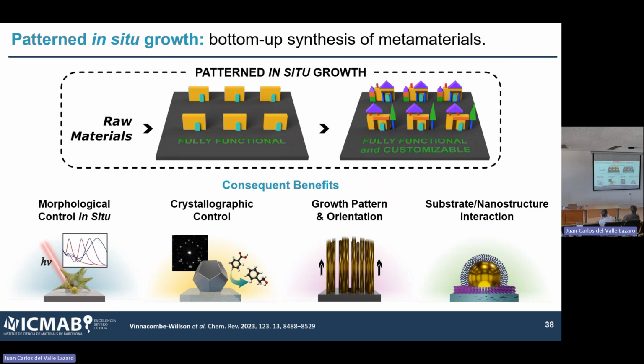And the other very important thing is that it opens up completely new possibilities for controlling the interface between my nanoparticle growing system and the underneath material, which is something that is really hard to do with self-assembly, because typically when we're dealing with colloids, we have a ligand shell, and that ligand shell will always be present between my particles and the substrate.